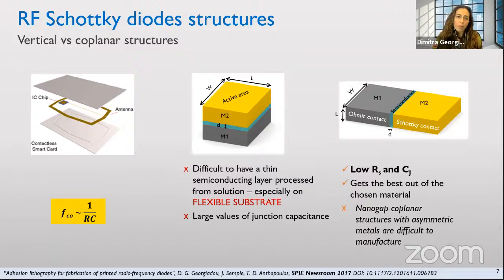For this reason, we propose a different device architecture, similar to the one shown here. This is a coplanar architecture where the metals are sitting next to each other and they are separated by a very short gap, and the semiconductor, the active layer, is deposited in between this channel. This way we can lower both the resistance based on the material that we use and the capacitance, because as you can see, we keep the footprint of the device the same, but this time the actual area is defined by the width of the diode and the length, which is the thickness of the electrode, while in the vertical device, it's always defined by the active area.